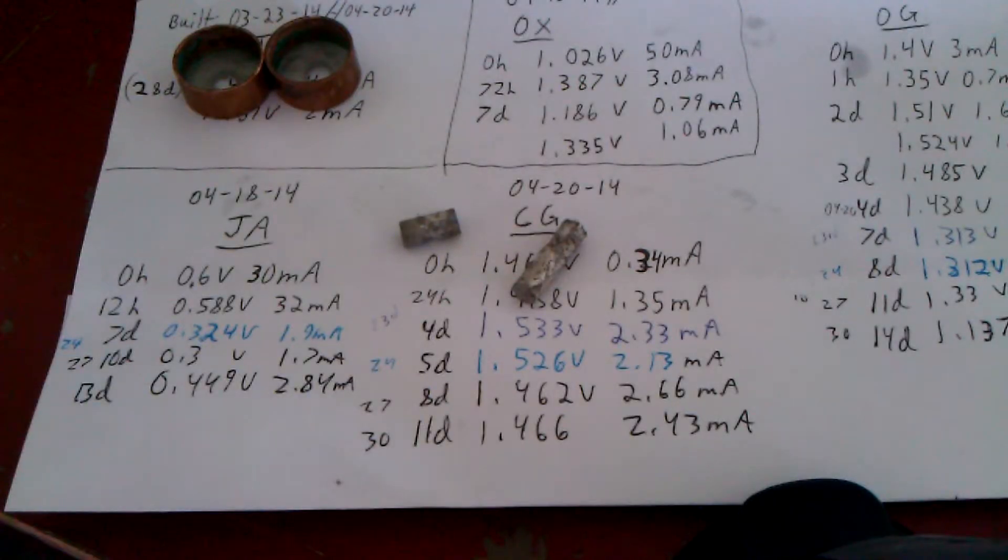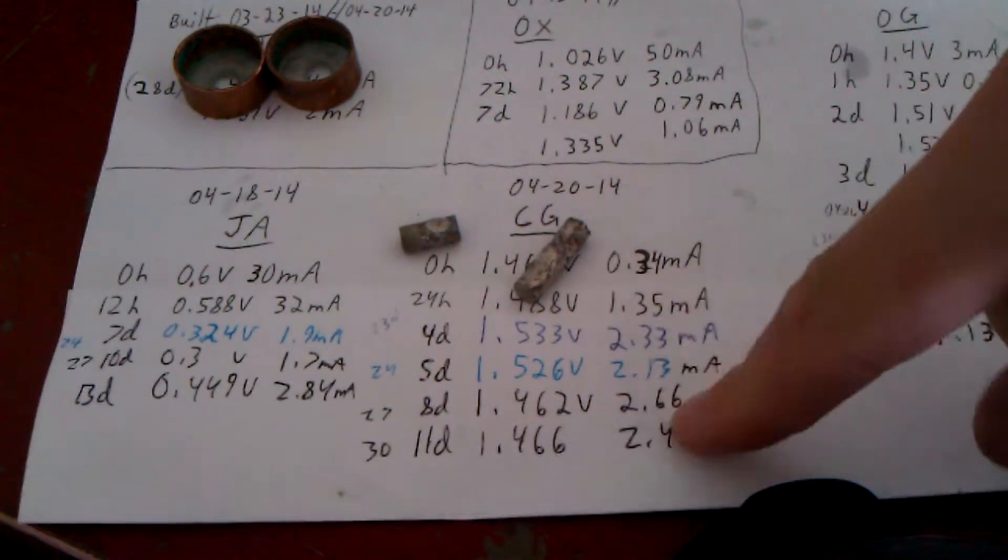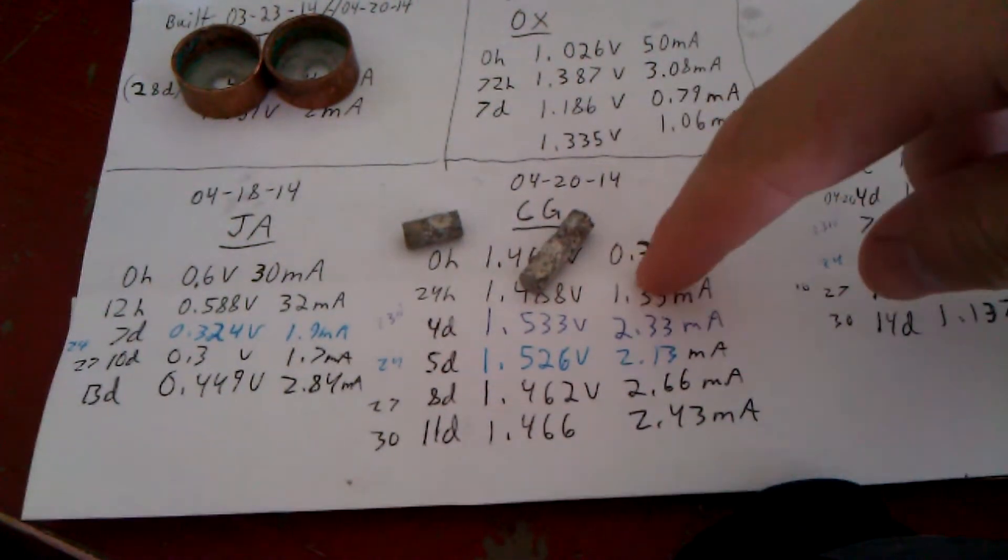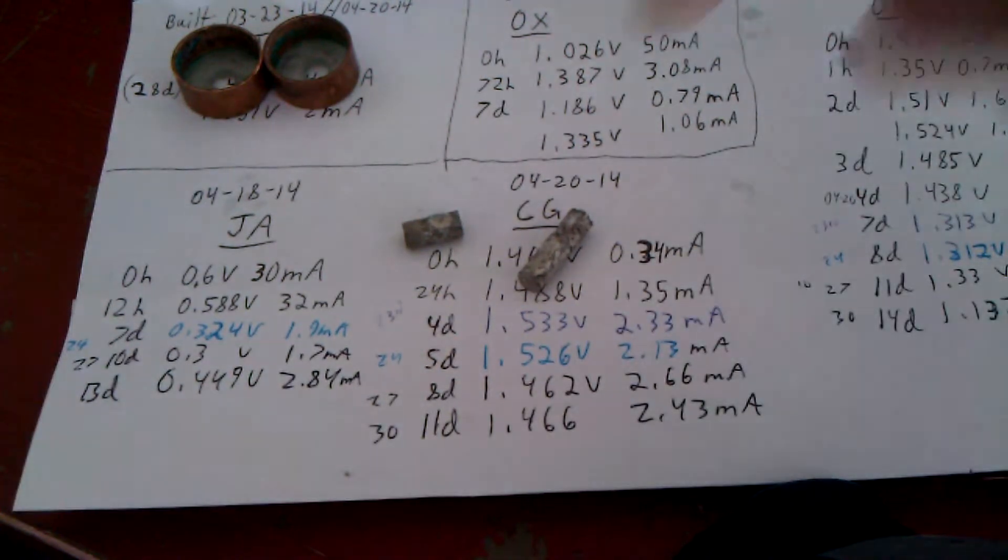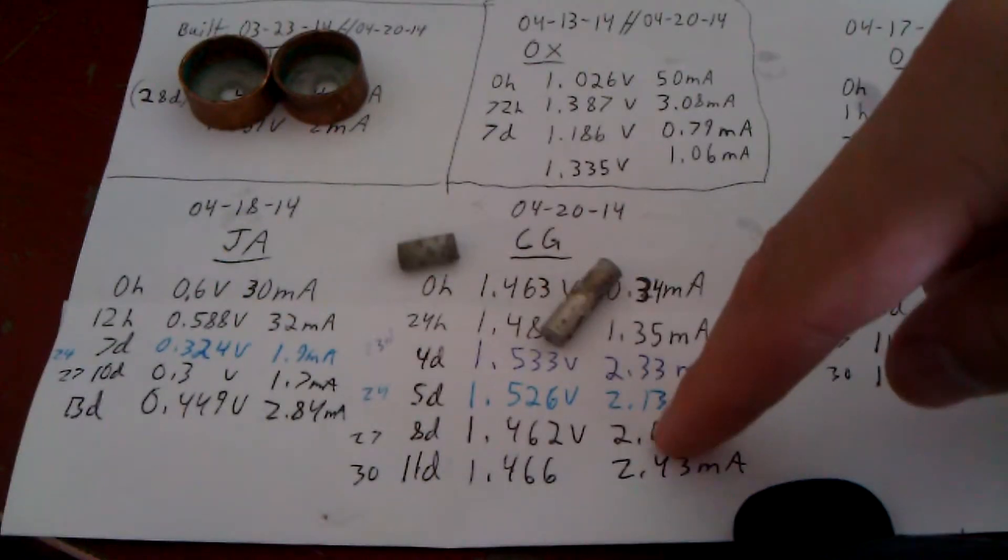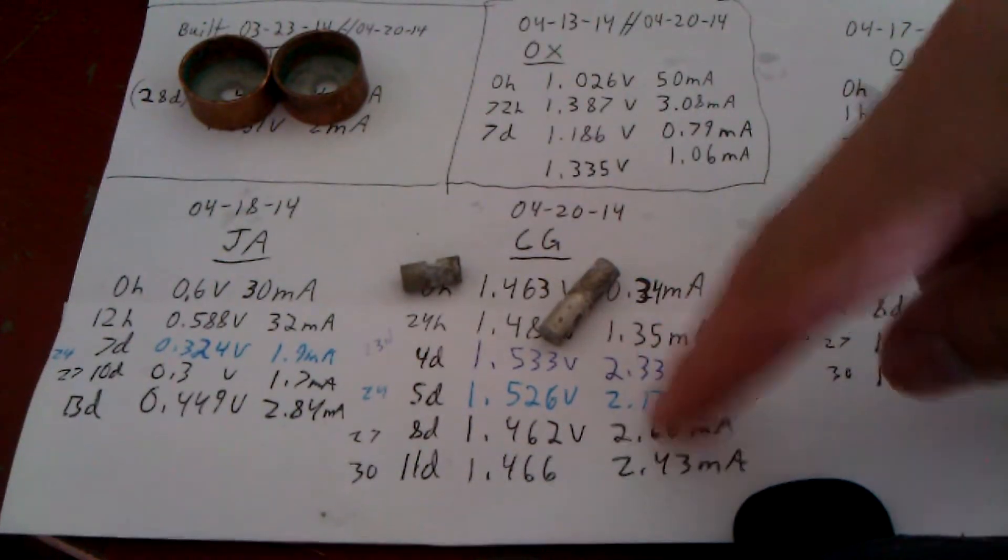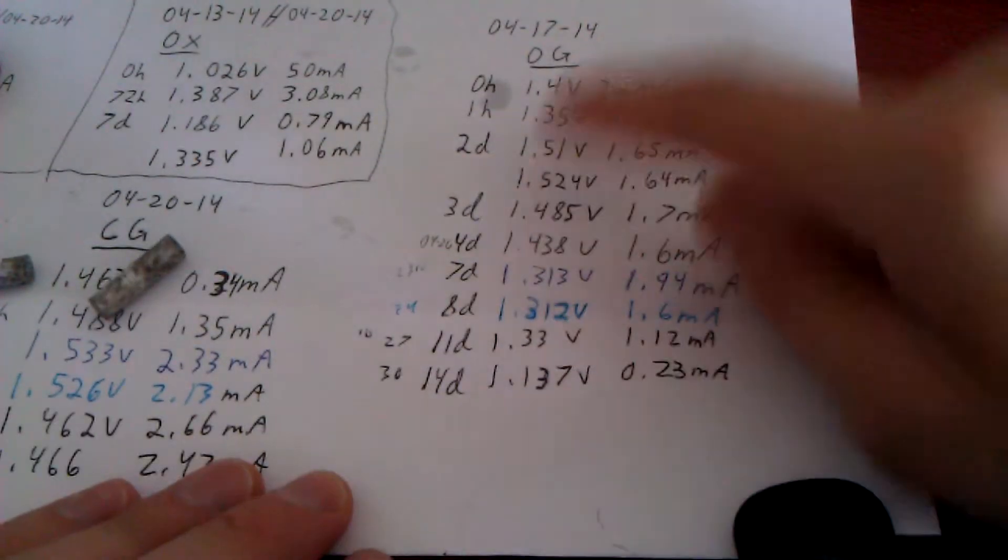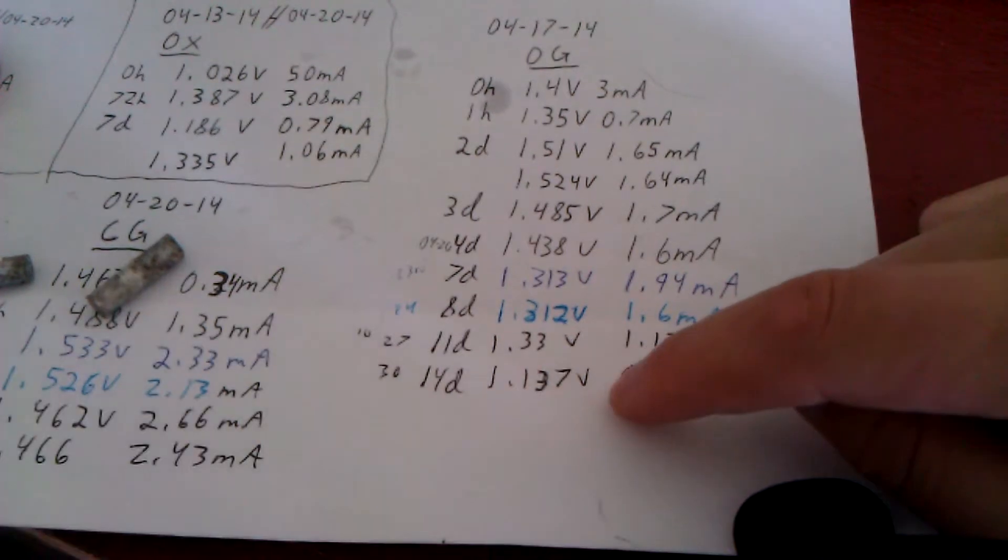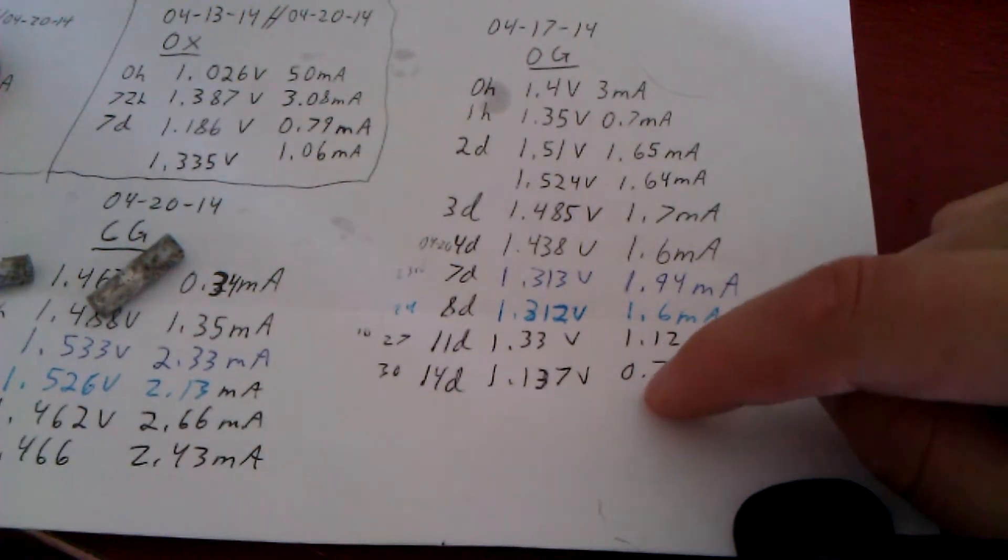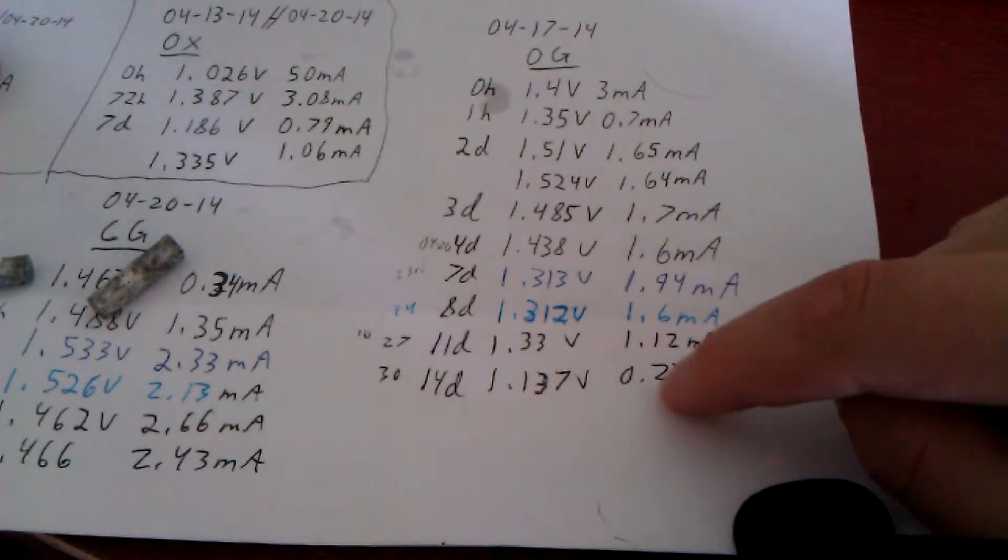You know, we definitely didn't solve the corrosion problem. But we've leveled off the current flow. So instead of getting 40 milliamps right away, and then within 12 hours, having it drop down to 10, we had it ramp up to 2, and stay at 2 solid for almost two weeks straight. And the exact same with this guy. I poorly built this cell. And I didn't put dielectric grease over everything. So that might have affected this.